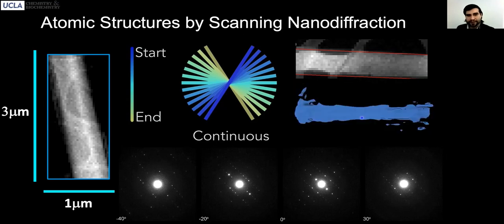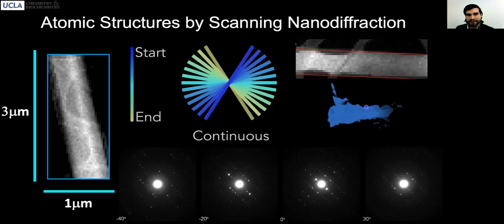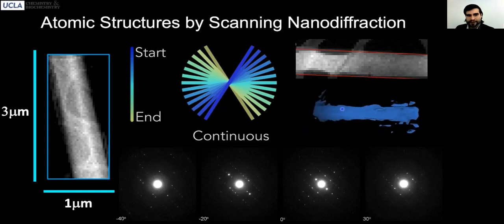In this case, you can do it three-dimensionally. You can reconstruct the structure of the crystal. Here you can see that reconstruction tomographically. And select only patterns that correspond to regions of space that are within the masks shown here. The patterns are shown here below.